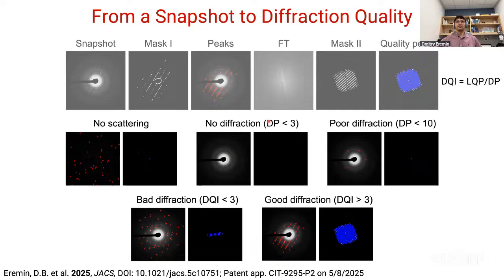If you have less than 3 diffraction peaks, that's what we call no diffraction. Sometimes some things might come through, which is why we are not exactly cutting it at 0. Poor diffraction is when you have less than 10 diffraction peaks, because that's definitely not going to be enough for you to solve any structure. But what's more critical is the differentiation between bad diffraction and good diffraction.